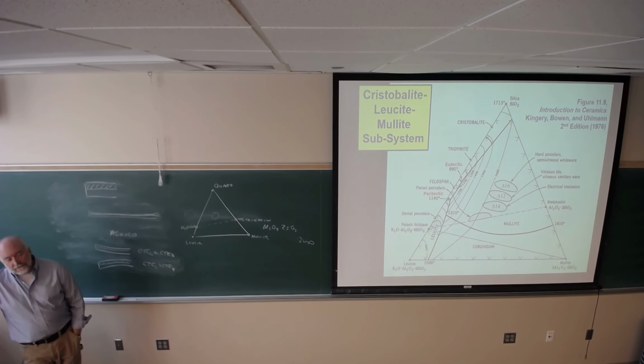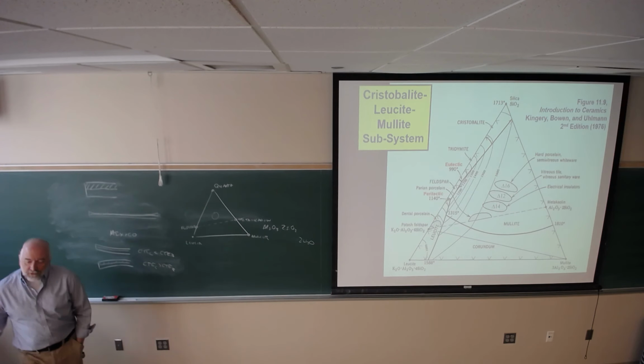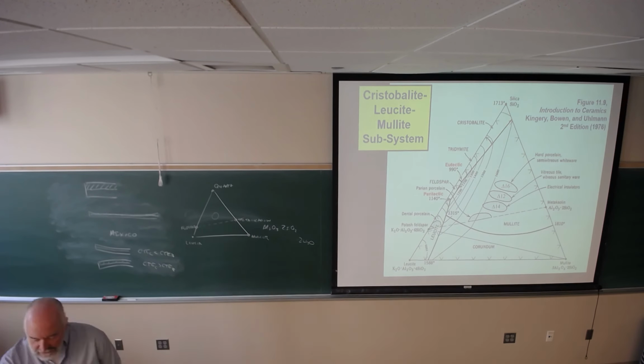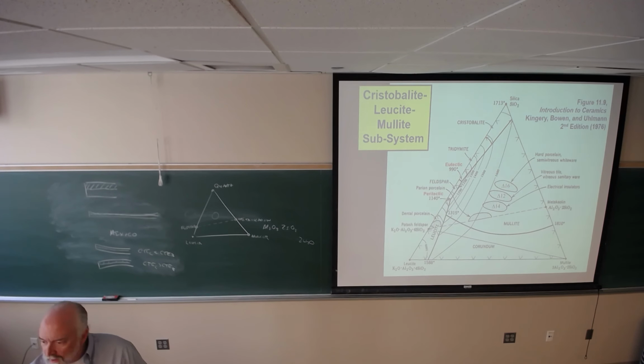So, it's somewhat of a trick question. It's because the industry dictated the firing temperature based on the properties that they needed out of the material. And that sort of tells you something, right? What that tells you is that we have a broad range of firing temperatures possible with porcelains in the first place, which is one of the beauties of the material. If I'm on the low end of the firing cycle, I can get properties similar to if I'm on the high end of the firing cycle, right?